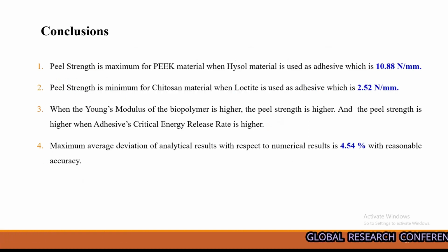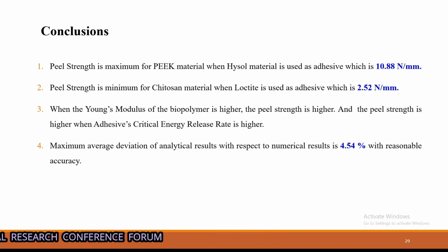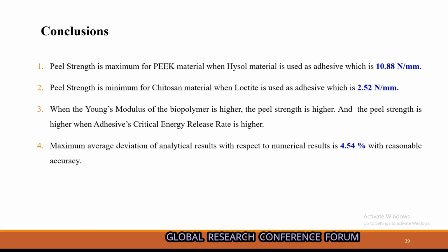This is the conclusion. Peel strength is maximum for PEEK, 10.88. Minimum for chitosan when Loctite is used, 2.52. Maximum deviation between the 2 results is 4.5%.